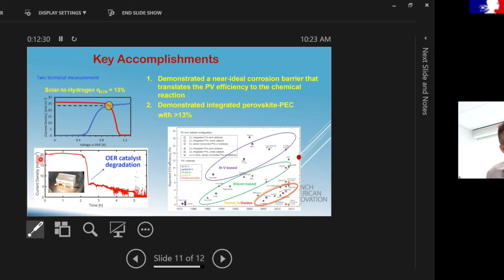Okay. And so this is a device which shows that it lives so far, and then you get this sudden degradation in this device. And this is because of the catalyst. We are not experts at making catalysts yet, and so our catalyst degrades. But now this has been improved upon, and we get at least about 10 hours of continuous stable performance. And so we are very excited about this. In fact, we have filed an IP for this and are starting a company with this.